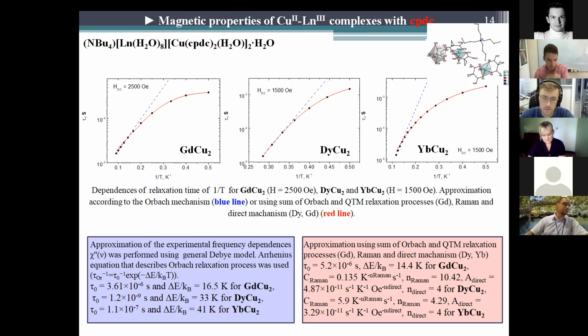In order to take into account the contributions of other relaxation mechanisms and for more accurate determination of the values of energy barriers, experimental dependencies were approximated in the whole temperature range using equations corresponding to sets of relaxation mechanisms. And for the best data, the agreement between theoretical curves and experimental data was achieved by using Orbach and QTM relaxation processes for the gadolinium-containing complex and Raman and direct mechanisms for dysprosium- and ytterbium-containing compounds.